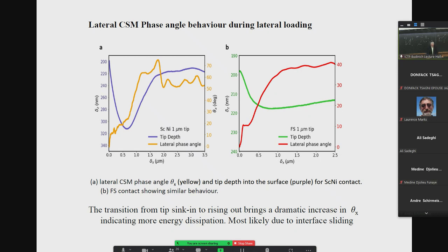Okay? So this is a clear signal that you've got interface sliding, and you've got a way of measuring that. So that localized interface we've been talking about is, of course, critical in this case. You can see evidence for this. Notice how when you get the initial sink in, the initial static friction, there isn't any. Right? That force is generated essentially by the geometry that you've made with the plastic deformation. It only comes about when the interface starts sliding. Okay. So that's one point.